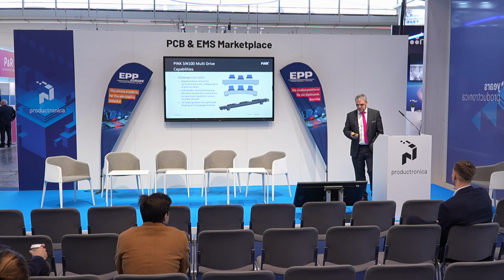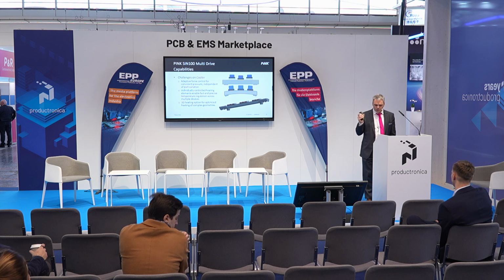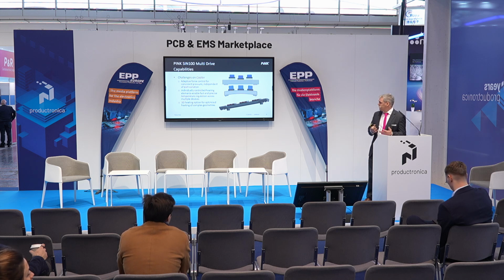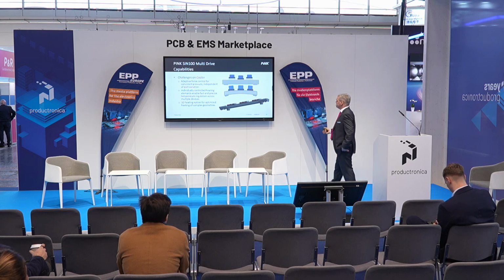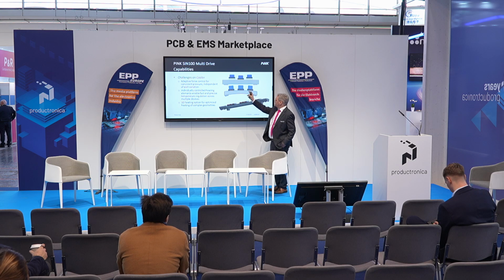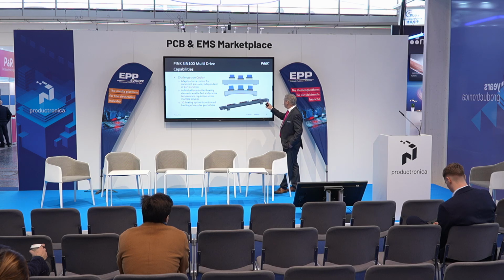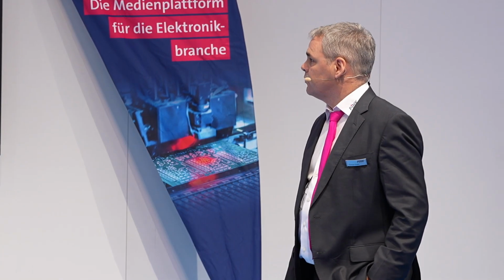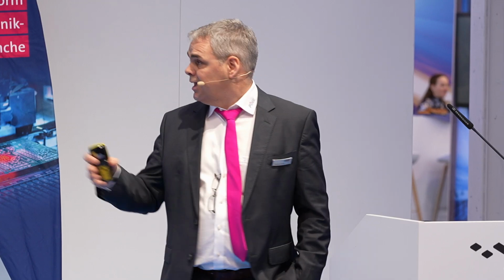So this is one thing I have introduced before. You may have failures or imperfections inside of your device. You may have different thicknesses of sinter layers. You may have a warpage on your part. You may have complicated 3D structures on the bottom of your part. And basically, you have to take care of that. You want to make sure that at any time, no matter how your device looks, it's the same pressure everywhere. The machine has to take care that I have the same temperature and same pressure at any time, no matter how the part is shaped, and that is done in our equipment.